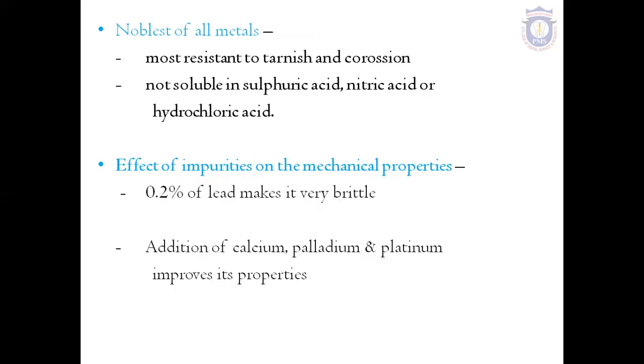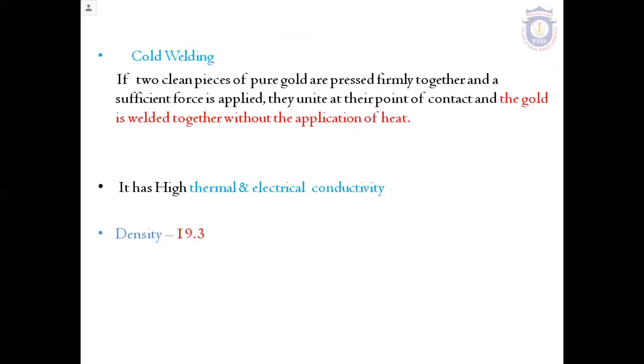Coming to the effects of impurities on mechanical properties, 0.2% of lead makes it very brittle, but the addition of calcium, palladium, and platinum improves its properties. In cold welding, if two clean pieces of pure gold are pressed firmly together and sufficient force is applied, they unite at their point of contact and the gold is welded together without the application of heat. This is a very important property. Simply with the application of pressure, two pieces of gold can be made to unite, and that is known as cold welding. It has high thermal and electrical conductivity. The density is 19.3.